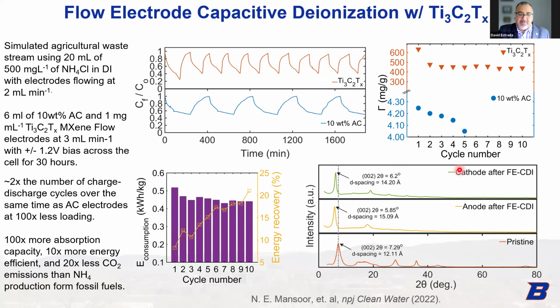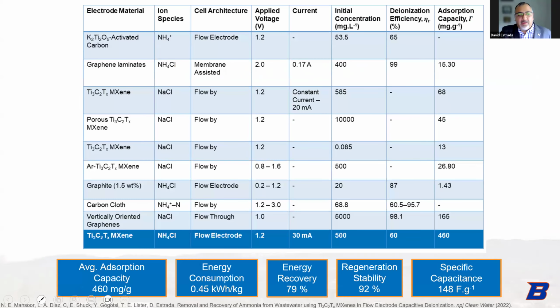Unlike activated carbon, where you only have the surface for absorption, we can get in between the layers here with the 2D materials. And then our energy consumption is about 10 times less compared to activated carbon. So we're 10 times more energy efficient. And if you were to synthesize ammonia from fossil fuels, the amount of ammonia we can recover would reduce the CO2 emissions by a factor of 20 for the same amount of ammonia.